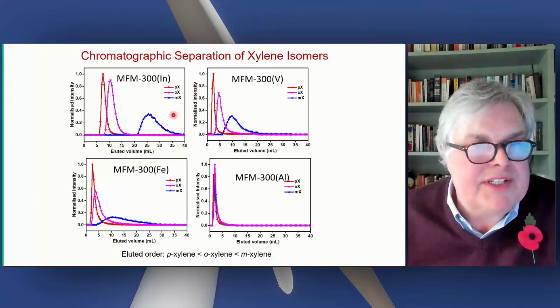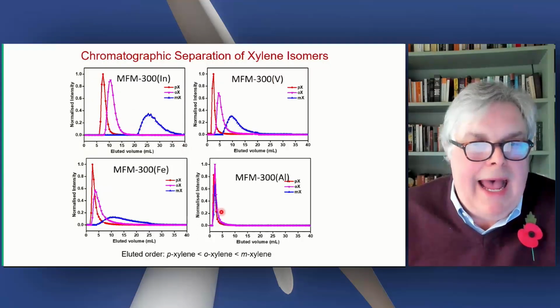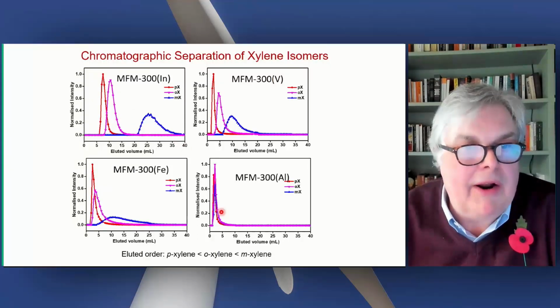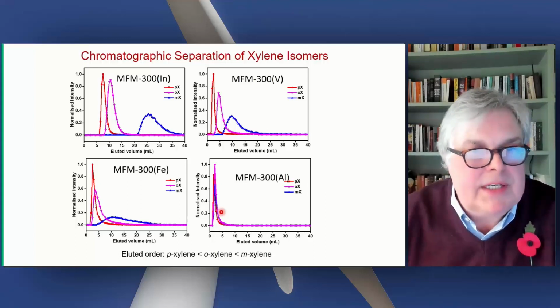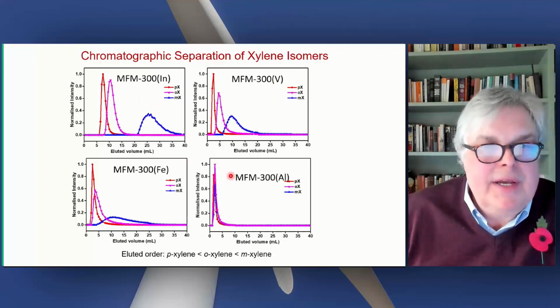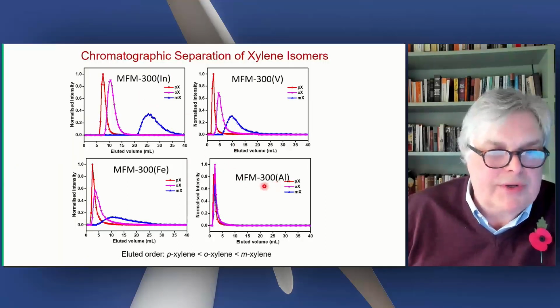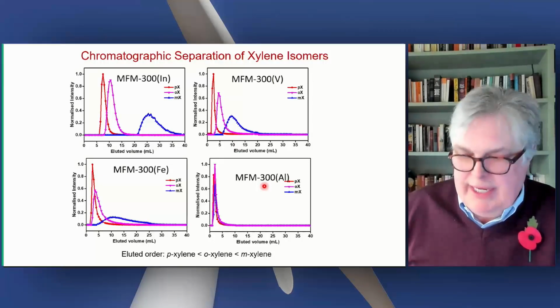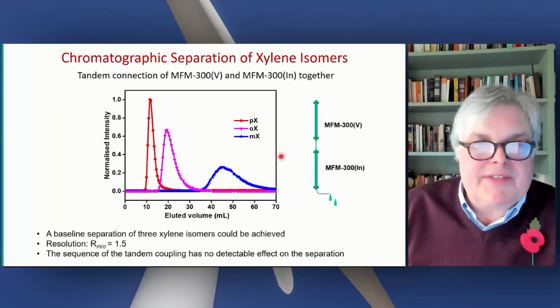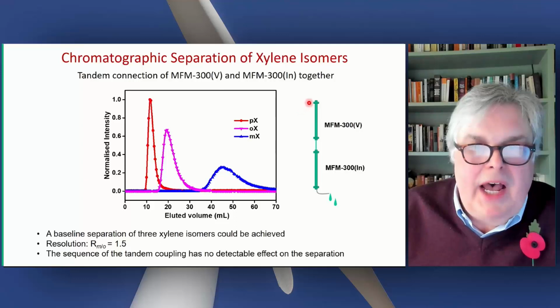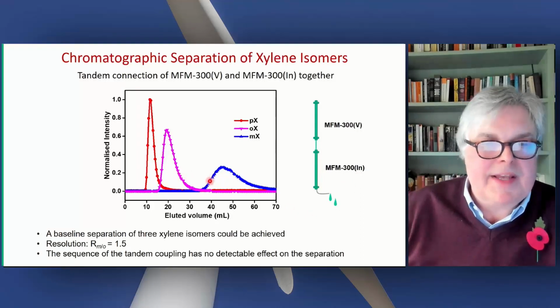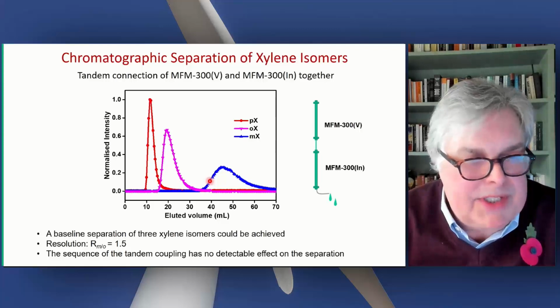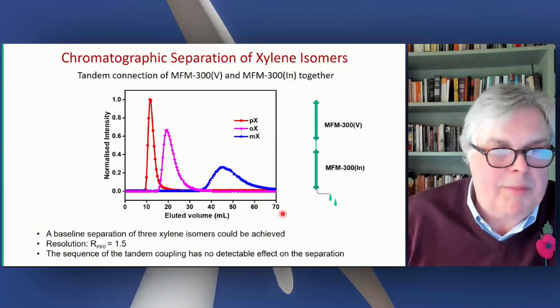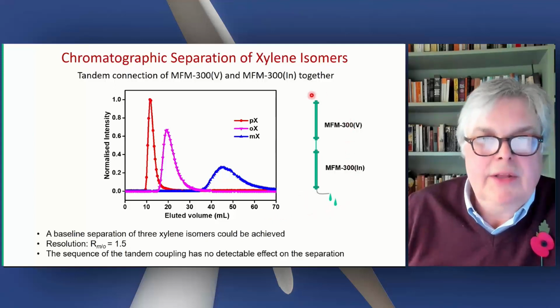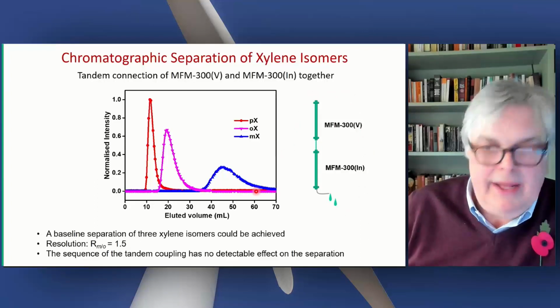And just to summarize, you can see indium separates quite well, aluminium separates not at all. So clearly we are in the right regime in terms of size, property, structure, function to see differences between aluminium and indium, even though they're isostructural. So the pore diameter and size is very important here. The best separation we've seen thus far is by actually passing para-ortho and metaxylene first through a vanadium column and then put it through the indium column, and you get this type of separation. This of course is academic research. I'm not suggesting this has solved the problem, far from it, but at the same time it illustrates that MOFs do have a capacity and potential in this area.